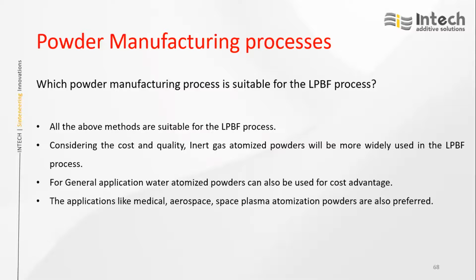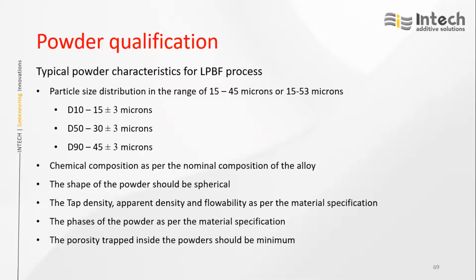The selection of powders purely depends on the kind of application. Typically, powder characteristics should be in the range of 15 to 45 microns, or 15 to 53 microns. If you elaborate, that means D10, D50, D90. D10 means 10% of the particles should have a size of 15 microns plus or minus 3 microns. D50 means 50% of the particles should have a size of 30 plus or minus 3 microns. D90 means 90% of the particles.